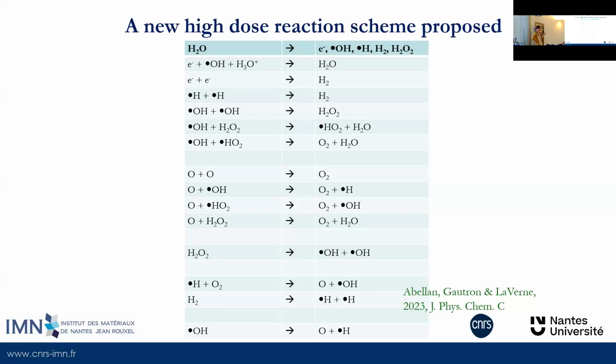Probably, but then the problem is you have the encapsulation. The problem with doing this with the water OH stretch is that your water vibrational OH stretch peak is dominated by the H-bond network inside the water.